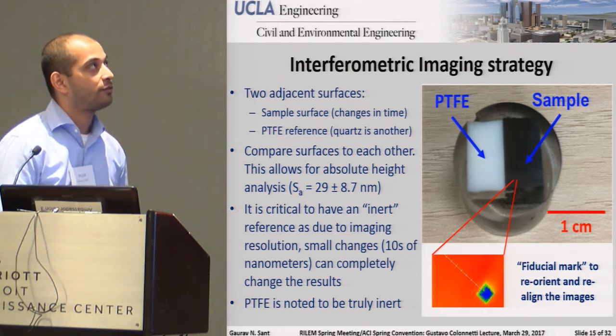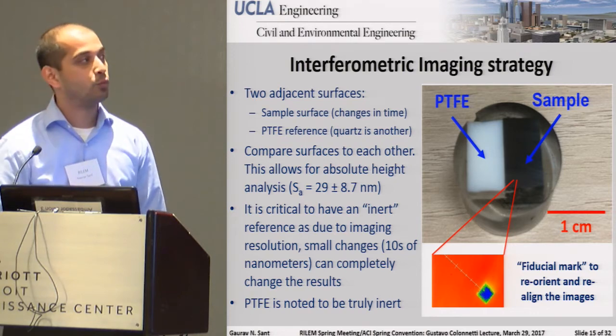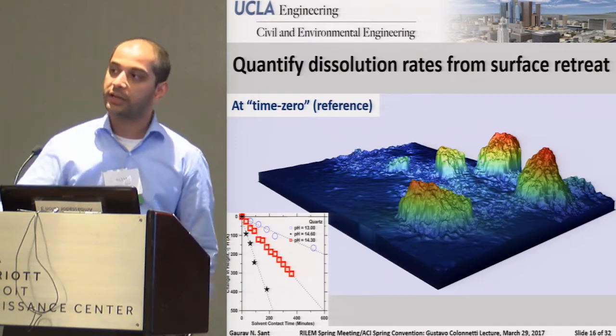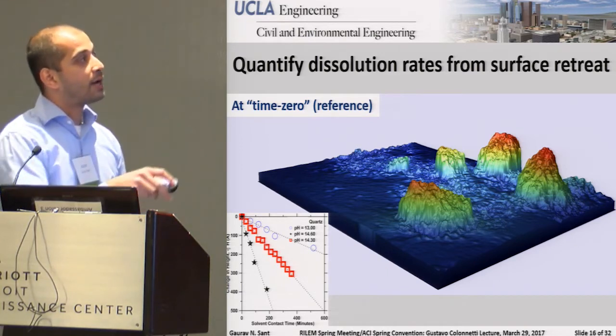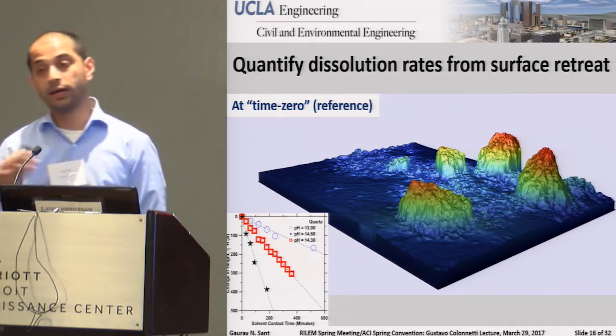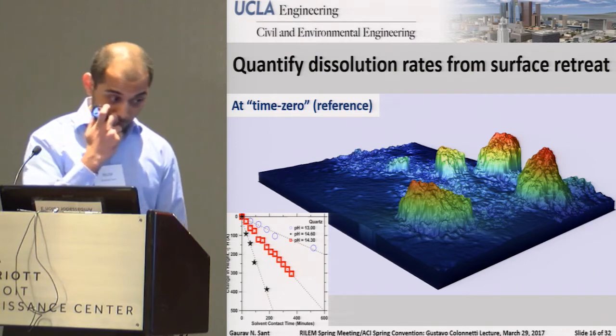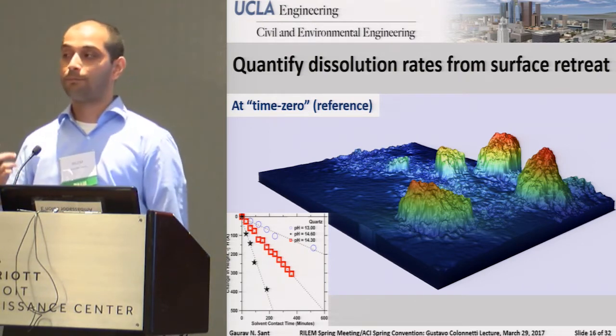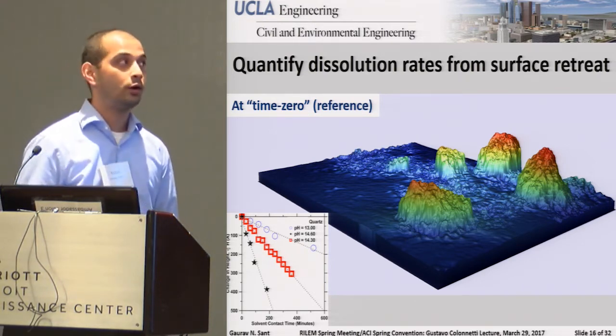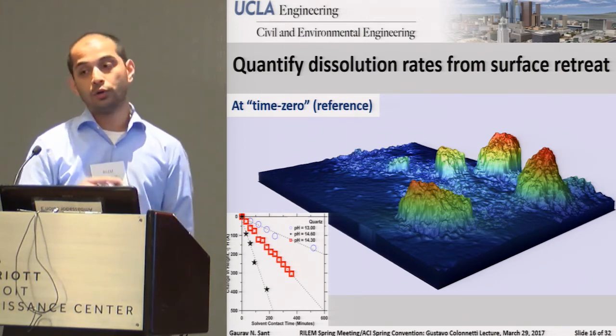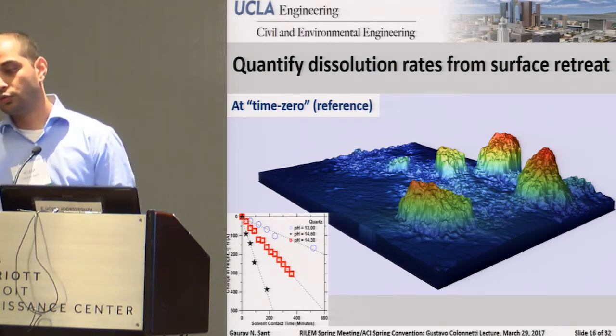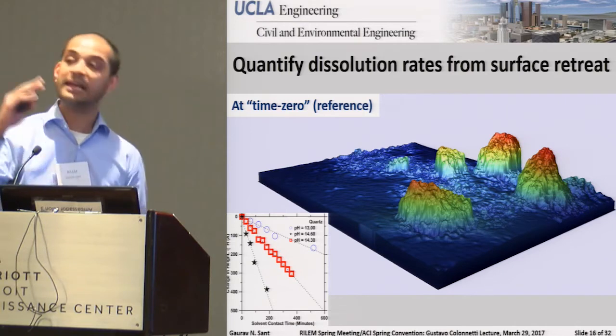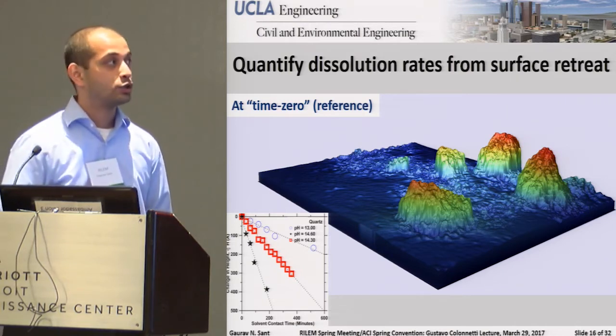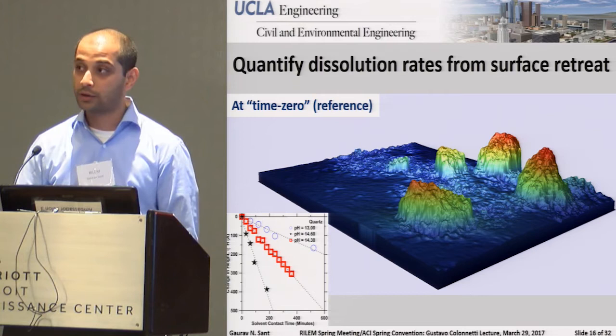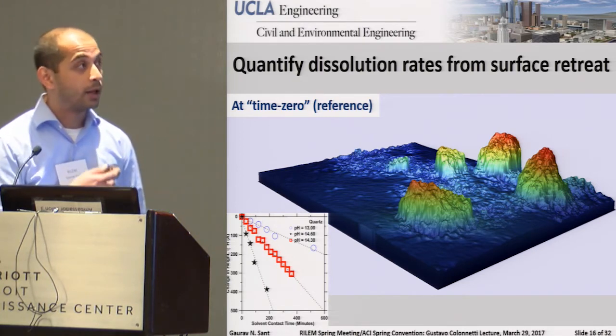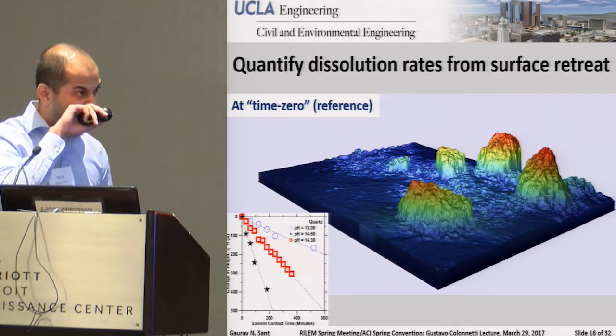So if you want to try and quantify dissolution rates, for example, from what I will call surface retreat, the surface retreating away from its original position, you can imagine that you've got a sample surface that looks like this. Now again, just one thing to point out, the nice thing about interferometry is you can do it with really, really highly polished planar surfaces, or you can do it with particles. So the way these interferometers work is you've got an effective measuring range of about 300 microns. So as long as your particles are smaller than 300 microns, you can actually measure them. And this is something that makes the approach really quite powerful.